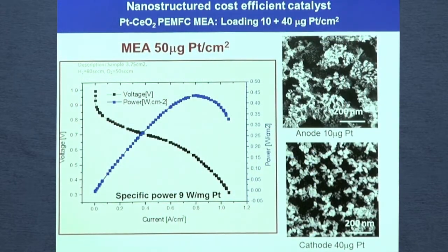We can also prepare thin film anode and cathode. In that case, the performance is not so high. We are at 0.5 watt, but the total loading of the MEA now is 50 microgram of platinum per square centimeter, which again is a very low loading.